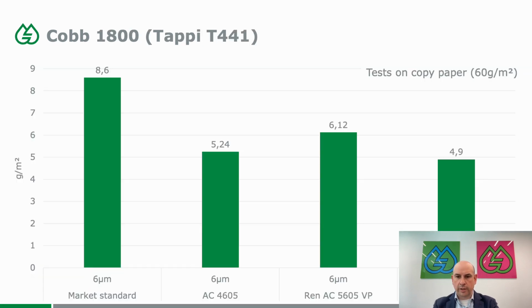So here you can see already that we choose to use a COBB 1800, so half an hour of testing, and all these tests were done on the copy paper, so that is important to understand for comparative reasons. On the left hand side you can see a market standard resin that we found with a COBB of 8.6, and you can see that The Alberdingk products that are offered in this market space are always better than the market standard and at a very, very low level, so around 5 grams per square meter, which is a very, very good result for a COBB test.